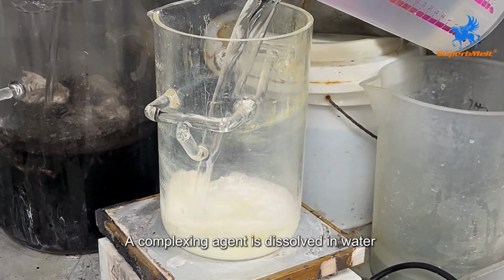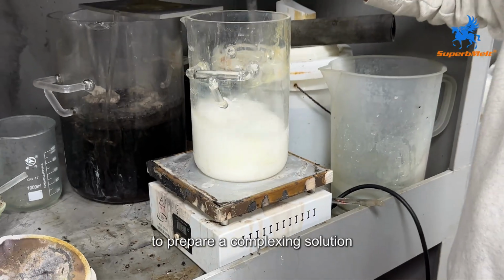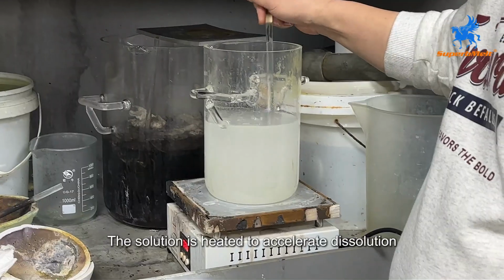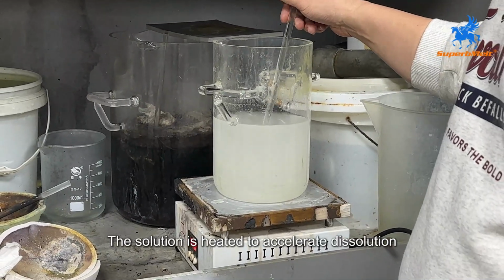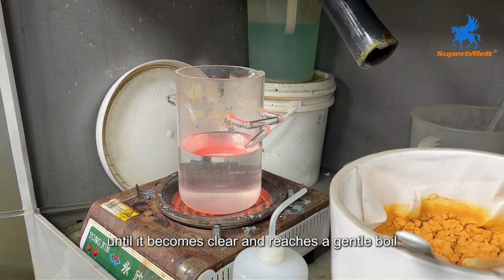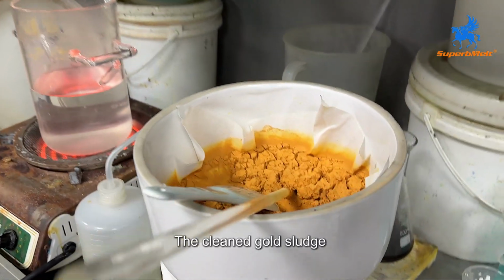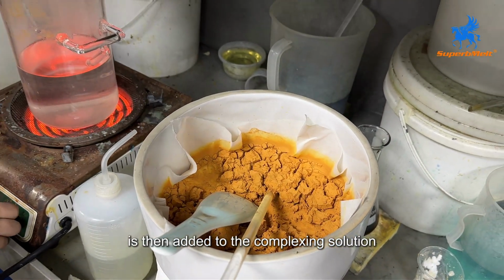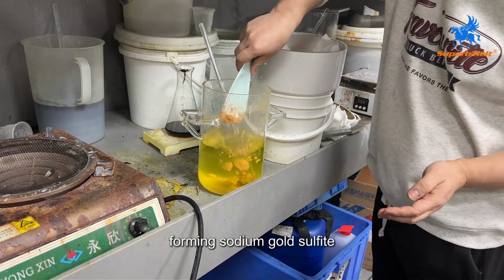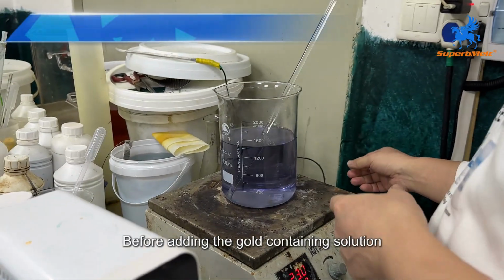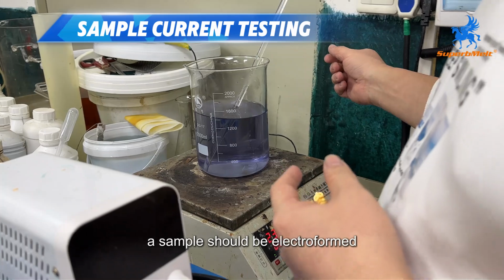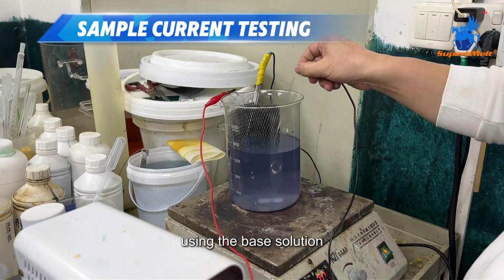A complexing agent is dissolved in water to prepare a complexing solution. The solution is heated to accelerate dissolution until it becomes clear and reaches a gentle boil. The cleaned gold sludge is then added to the complexing solution, forming sodium gold sulfite. Before adding the gold-containing solution, a sample should be electroformed using the base solution.